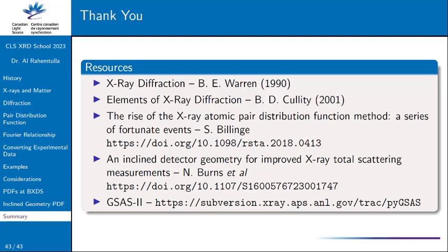One of the problems I didn't touch on is that as you get closer and closer, the problems that start emerging are the effective parallax and absorption. As you get really close to your detector, you're coming in at really sharp angles, and at high angles those corrections start getting more complicated. You need to know more about your detector in terms of the layers that are there and the attenuation that can happen based on materials.